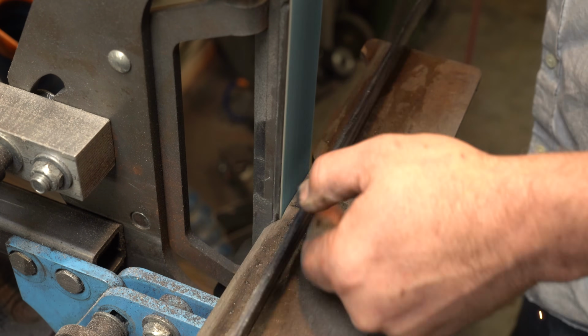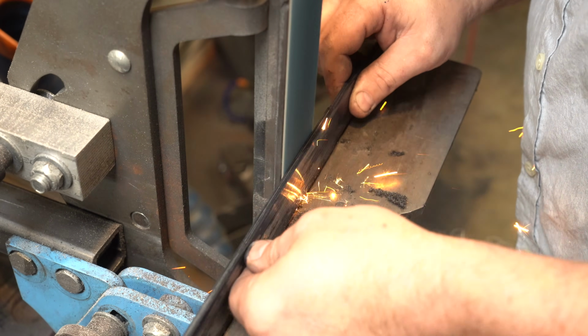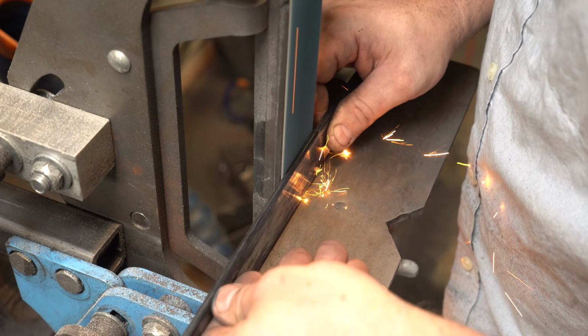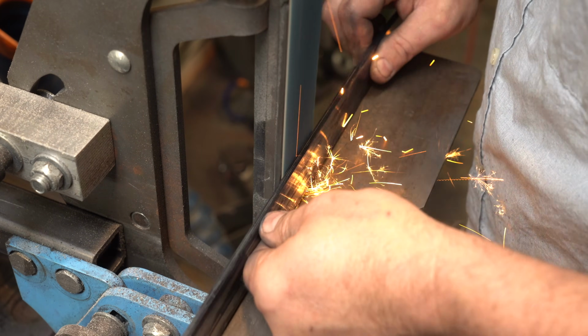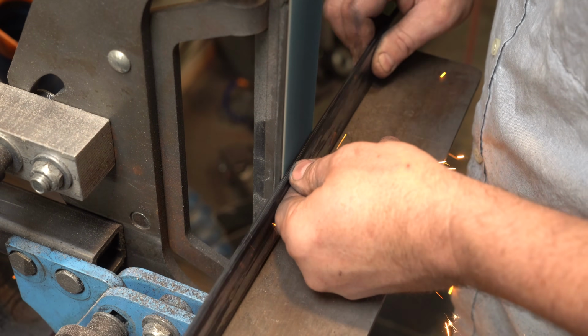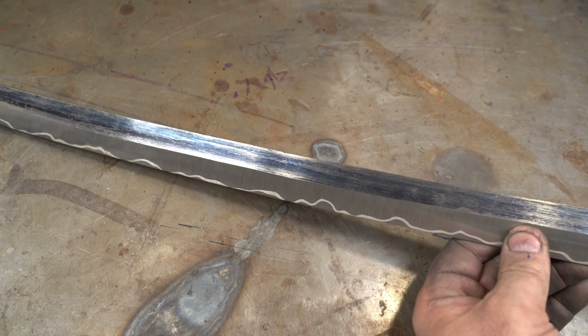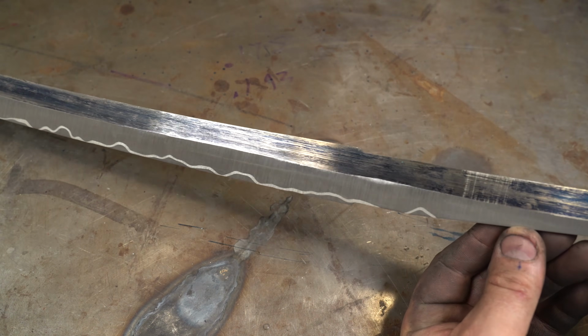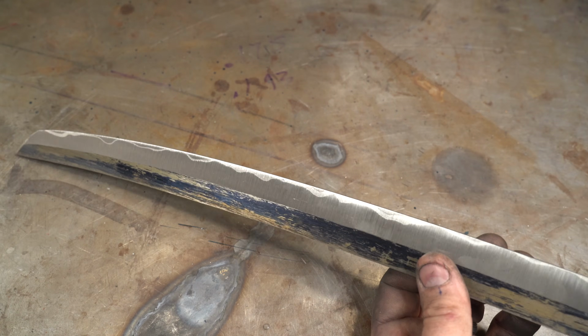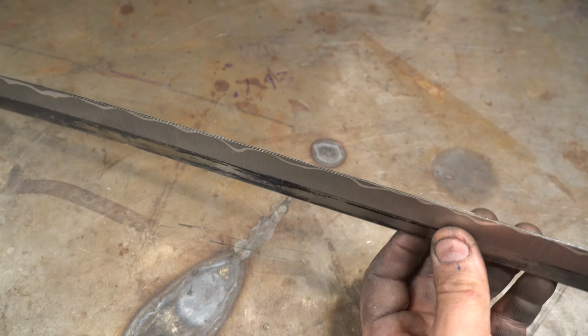Grinding this sword took several hours. It's kind of unwieldy to have to pass it back and forth across the platen, but I got it done. Here's a look at the bevel grinds. Of course, this is pre-heat treat, so these will be refined later, and that silver streak will move up the blade.